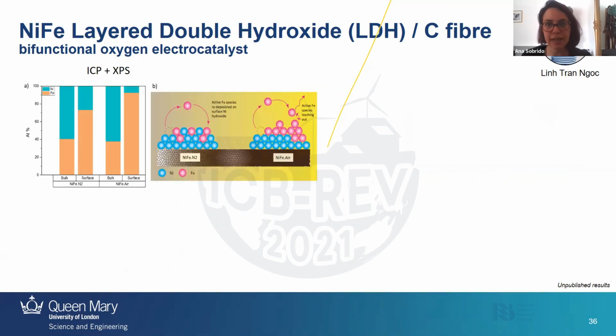And then the latest thing that Link's been trying to understand is to combine the ICP measurements with XPS measurements. What she's found, and this could be very key to understand this, is that in the case of the material prepared under flowing nitrogen, the surface contains a little bit more nickel than the one prepared under static air, which contains a lot of iron. So that might be it. And that might be why the bulk seems to be the same amount. So that might be why we are getting this difference. That might be the key, but we still need to know why exactly.